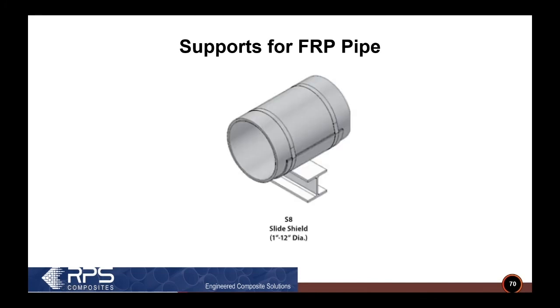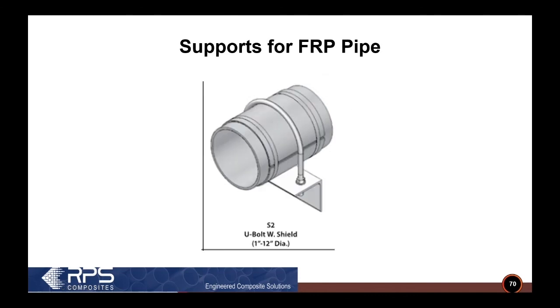The styles of FRP pipe support: the most basic FRP pipe support you're going to see is just a shield. So this shield could be FRP, it could be metallic. It's strapped onto the pipe, and you can see that on the I-beam in the picture. Normally in steel, you might just lay the pipe right across the I-beam. That would be a no-no in FRP. You'd want to have at least a shield, which has that rubber liner and is strapped onto the piping. If I needed to guide that piping, remember I said maybe every fourth support needs to be a guide, you could put a U-bolt, but now if I put a U-bolt over the top of the piping, I'm going to need a shield on the top side as well.